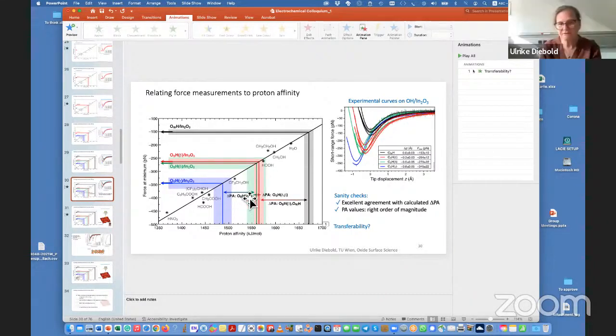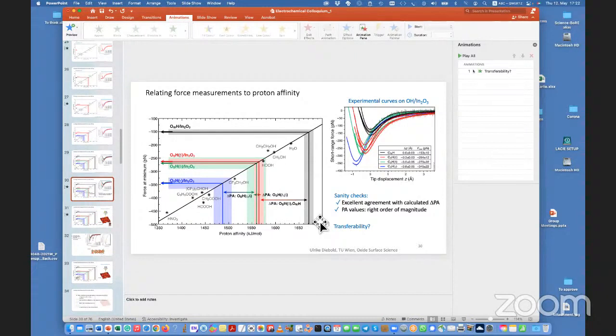And then you compare that difference with what we measured. Through the line, we go to the x-axis, and this x-axis can be calculated independently. So these are independently calculated and independently measured. From the measurement, this calibration, we go down, and that fits quite well. What you cannot do is absolute values in DFT, but the relative ones you can calculate by moving from one to the other. Does it make sense? Those are in gas vapor, right? Yeah, everything, this is DFT.